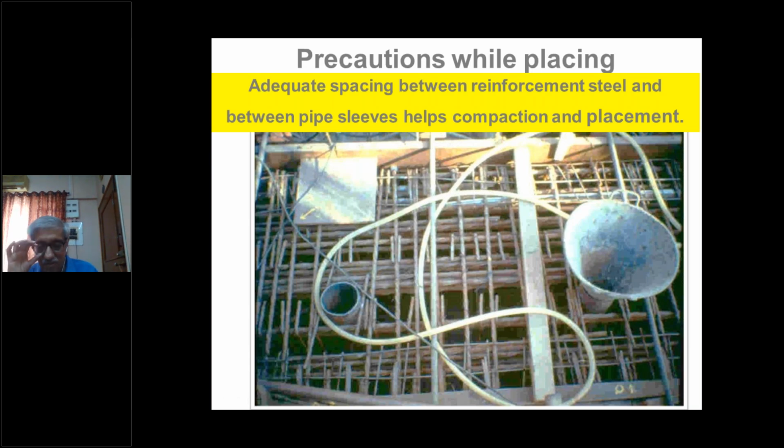If this does not clear the density of the reinforcement, you are allowed to bunch the bars. Preferably avoid any horizontal laps at one place. You can stagger the laps. An alternative is also to use bigger diameter bars instead of many smaller bars. This will permit you to reduce the segregation and have a more comfortable way of concreting.